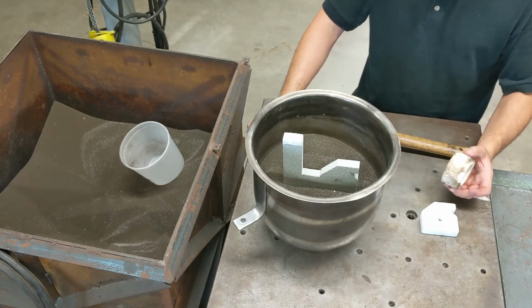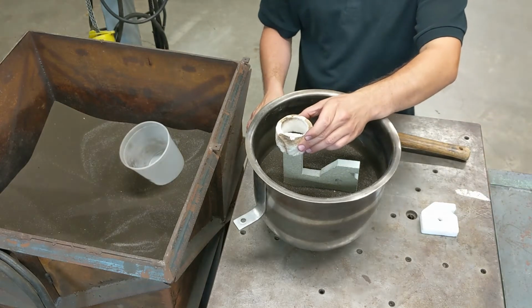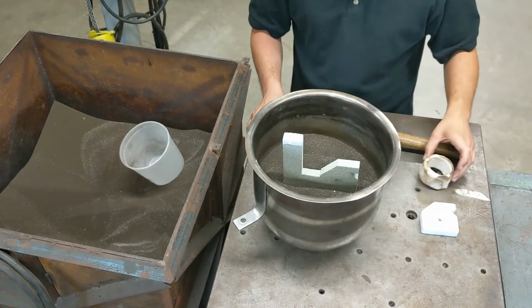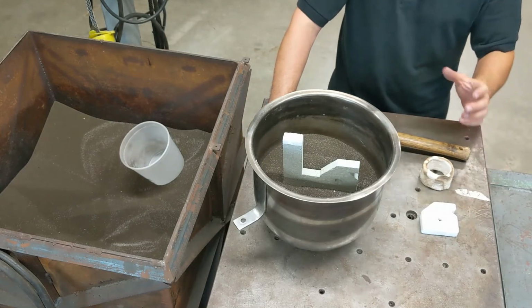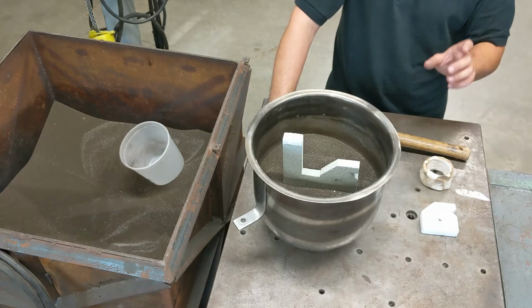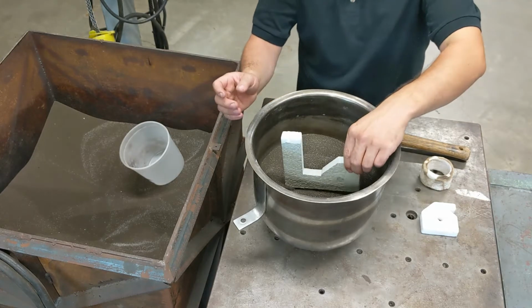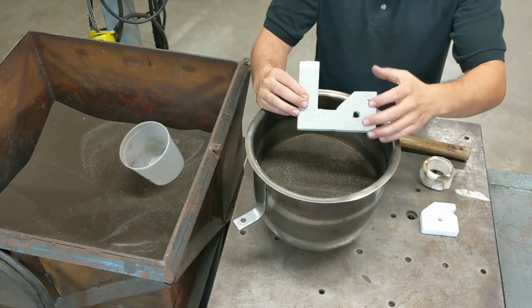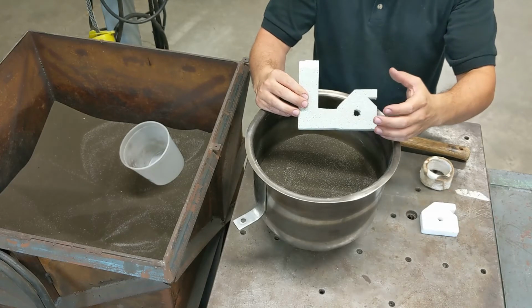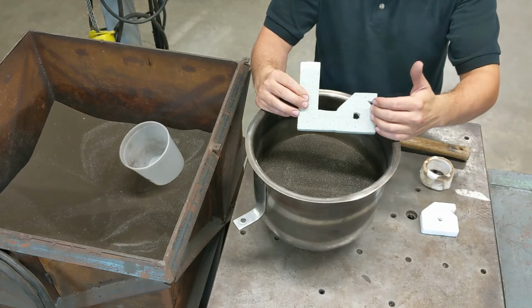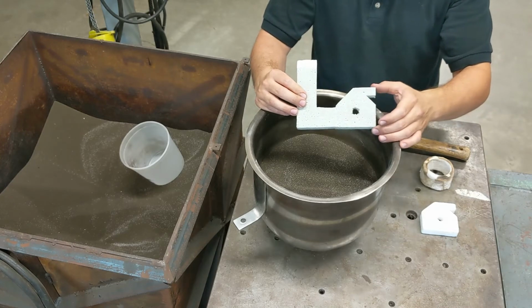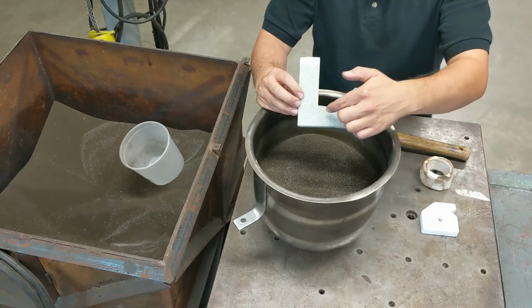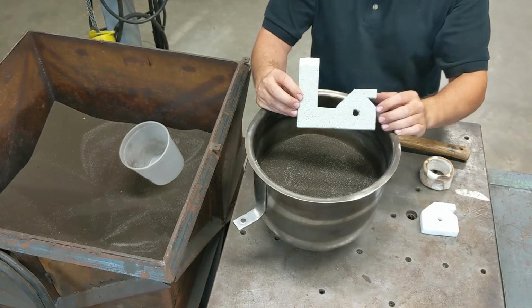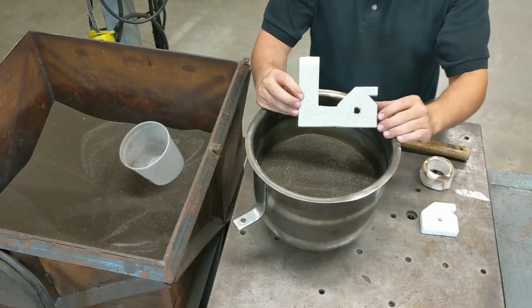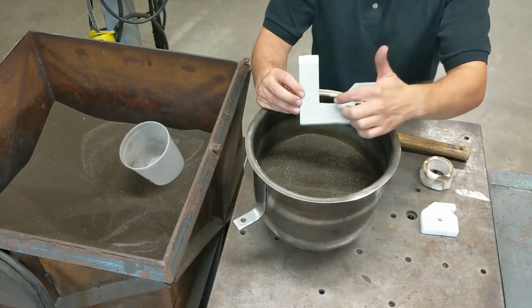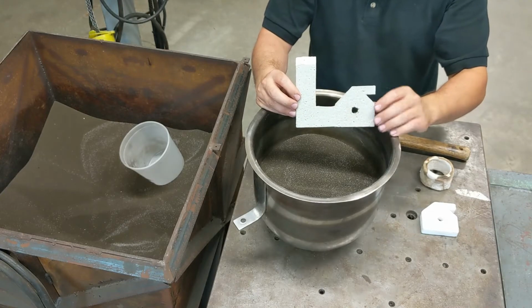The last thing I'm going to do is put an insulating sleeve on the top of the pouring sprue, and the reason for that is that I want the pouring sprue to be the last piece of metal to solidify. As this whole casting solidifies, it's going to shrink. And as it shrinks, it's going to pull in metal from surrounding liquid areas. So by keeping the last area to solidify over here in the sprue, any defects that we get as a result of that shrink will end up in the sprue. And that's the part that we're going to cut off, so we don't really care if that gets some defects.